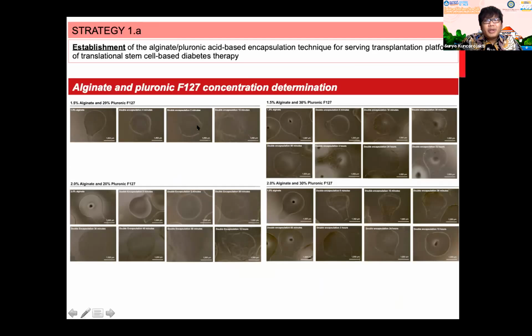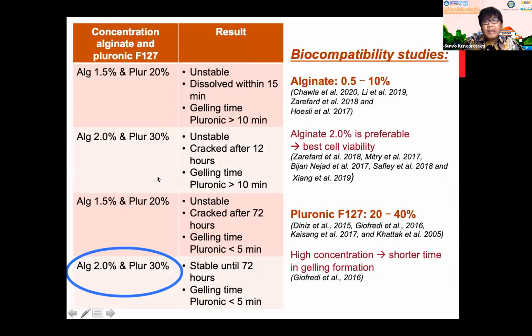The result was not satisfactory when we used 1.5% alginate and also 20% pluronic, because after double encapsulation, the capsule broke out. Then finally, we found the best concentration for the encapsulation. We found that 2% alginate and 30% pluronic is the best choice for this platform. Here is the result of our study, and the last platform that we did for the study.